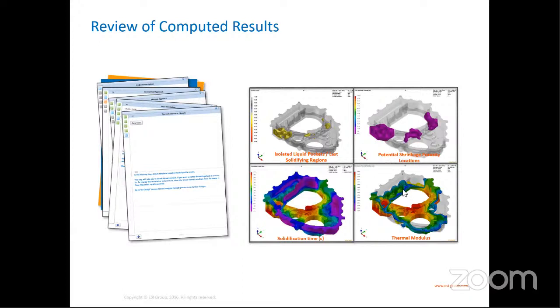If you perform such a simple simulation of solidification only, one can see quite nicely the problematic areas from the solidification point of view. So again, this can mean that we have some problems, and to find the solution based on this knowledge, to redo the design based on this knowledge, would be the first step to produce the final casting without a problem, and very nice.